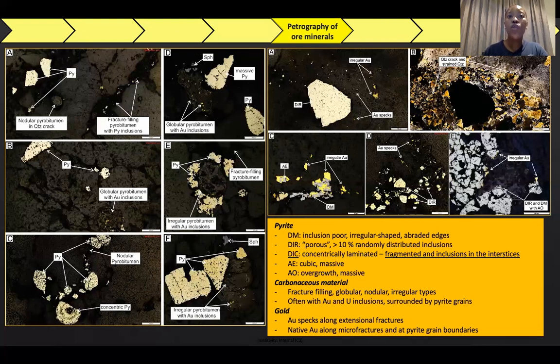The carbonaceous material also occurs in four main subtypes based on morphology, such as fracture filling, mostly in shales; globular, which often contain the most irregular shaped and micron-sized gold and uranium minerals; nodular, which are relatively smaller and rounded; and irregular shaped, which occur mostly within the boundaries of pyrite. And lastly, the gold, where gold occurs as native gold along quartz microfractures and at pyrite grain boundaries.